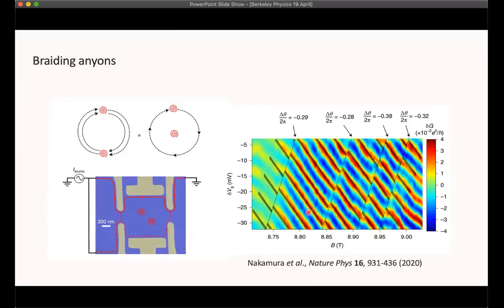So this phase slip, it turns out, is occurring when the field conditions are sufficient that they actually kick out a trapped particle. So what that's doing is it's changing the number of particles inside the braid. So what happens when you change the number of particles inside the braid? Well, you actually measure the statistics of exchange for these particles. And in fact, the phase slips, if you go and quantify them, were neither pi nor 2 pi nor 0. They were 1/3 of 2 pi.